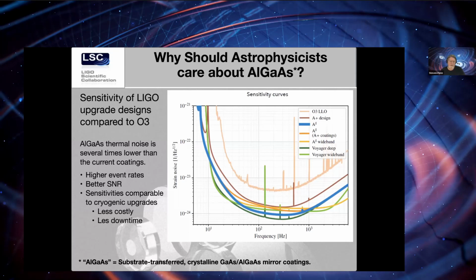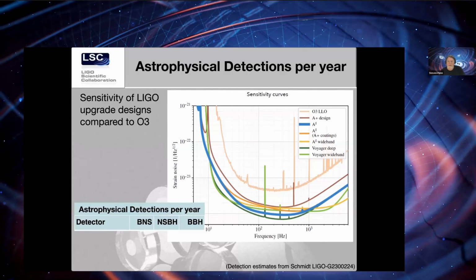And what this gives us astrophysically is higher event rates, better signal to noise ratios, and sensitivities for room temperature detectors that will compare with the designs for cryogenic upgrades. And the huge benefit there is that the room temperature detectors are less costly, there is less downtime, and there's less complications from going to a cryogenic system. It's basically known technologies that we can use by increasing the laser power, increasing squeezing, increasing the test mass size, and switching to crystalline coatings. That also translates into more astrophysical detections per year.